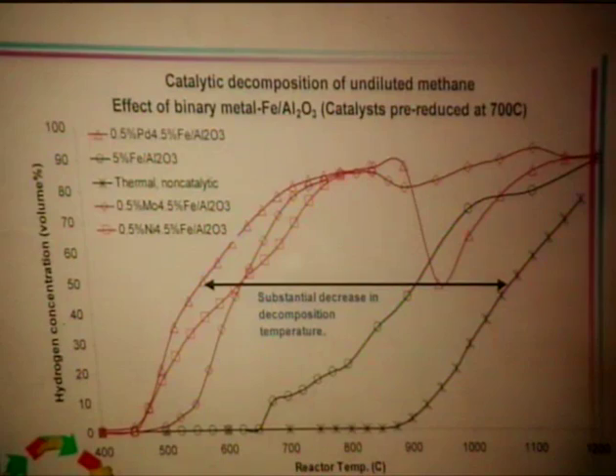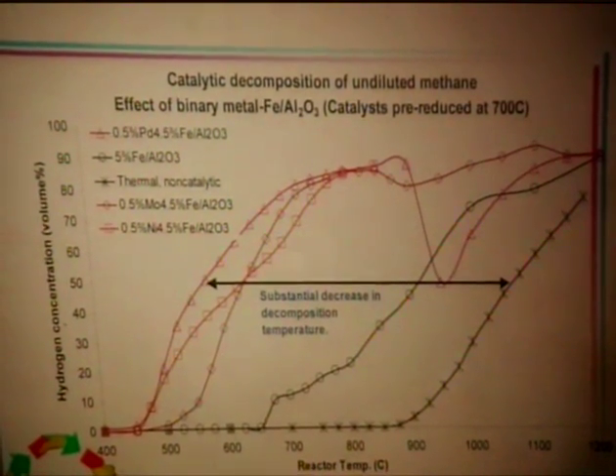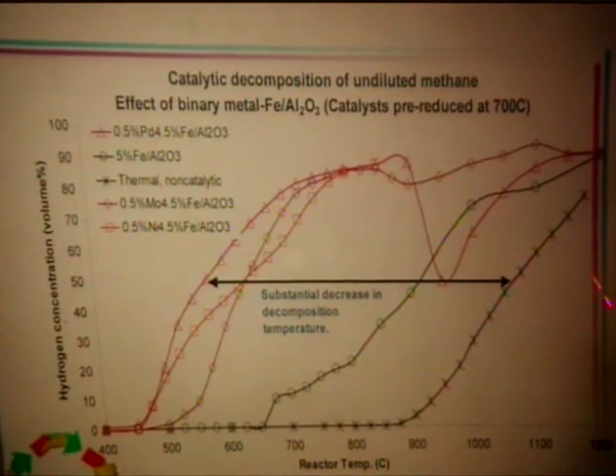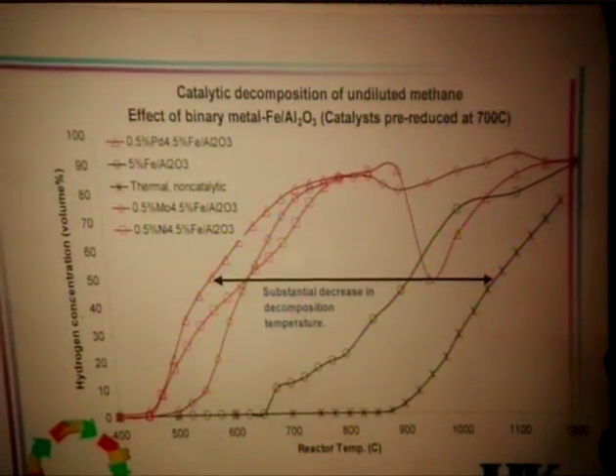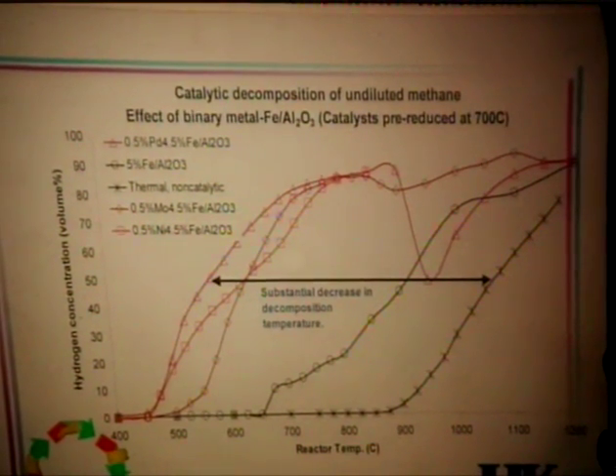Overall comparison of binary and monometallic catalysts pre-reduced at 700 C. Overall, the binary metal iron catalyst shows better activity than a monometallic iron catalyst pre-reduced at 700 C, and we were able to substantially decrease the decomposition temperature to around 400 to 500 degrees centigrade.